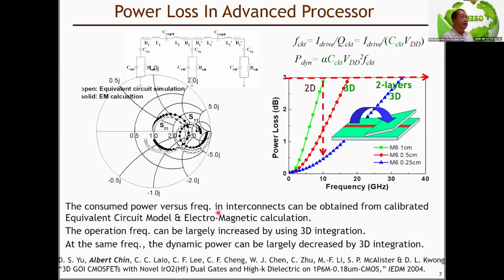versus frequency in the interconnect can be obtained from the calibrated equivalent circuit model shown here, and electromagnetic calculation using S parameters. This is the result. This is the power loss as a function of the frequency. As you can see now, the operational frequency can be largely increased. You can see the red arrow here. Using 3D or 2 times 3D, the operation frequency can be increased a lot. And at the same frequency, the dynamic power can be largely decreased by the 3D integration.